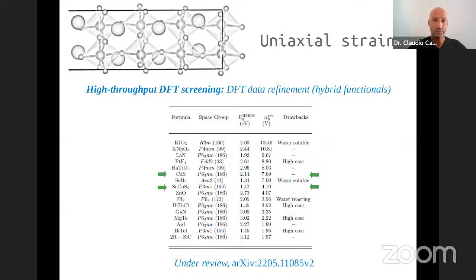Interesting other materials that we also found, because they were not considered before or haven't been considered yet in experiments, are this cadmium sulfide and this other scandium copper sulfide material, which are known from different contexts. Again, this is known also for its optoelectronic properties, but according to our calculations, if you put this material under ultrasounds or under mechanical actuation, it may be also quite a good piezo photocatalytic material. Then there is this other material known in the context of topological insulators, but not in the context of catalysts or photocatalysts, which seems to be also pretty promising, etc. So there is this long list.